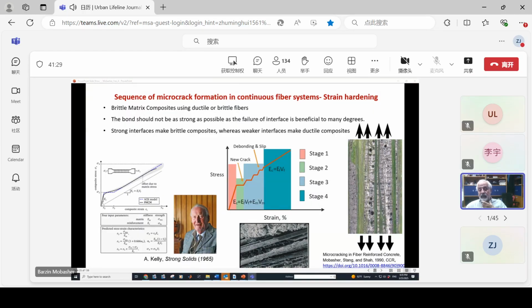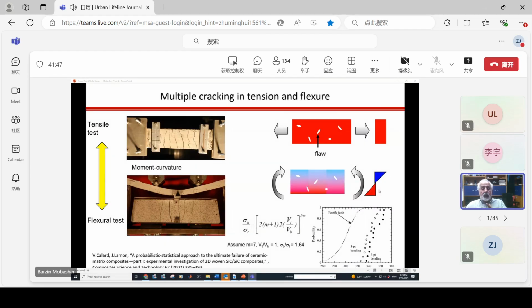And we have shown that more than 30 years ago, that cement-based materials can be made this way. And this was done a long time ago, 1990, the paper came out, 35 years ago. So we need to capitalize on this, and we need to show why these properties are this way. For example, if we do the same material, tested in tension versus tested in flexure.